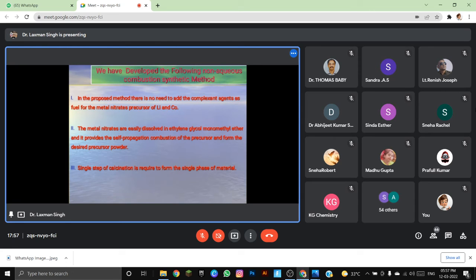So we have developed the non-aqueous combustion synthetic method. This is also known as the flame synthesis method. The beauty of this method is that we just need lithium nitrate and cobalt nitrate, mix them in an organic solvent and put them on a hot plate, and within 50 minutes we can get lithium cobalt oxide nanocrystalline particles in a single step. We do not need pre-calcination or evaporation of the gels and other organic and carbonate metal.